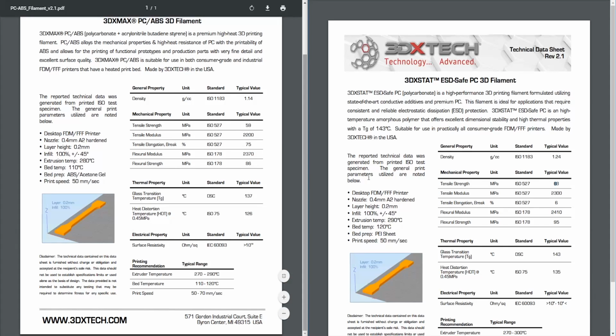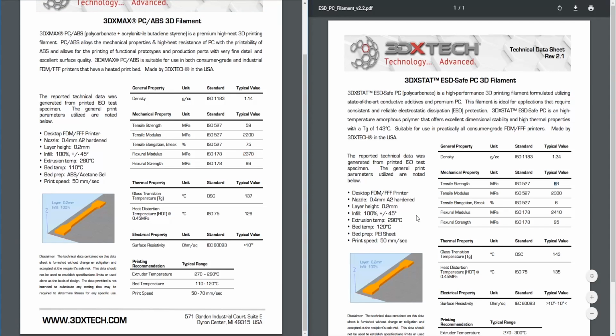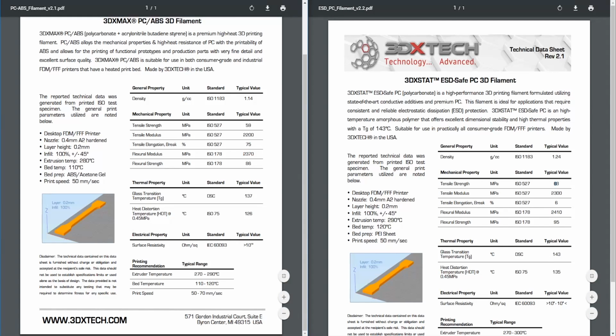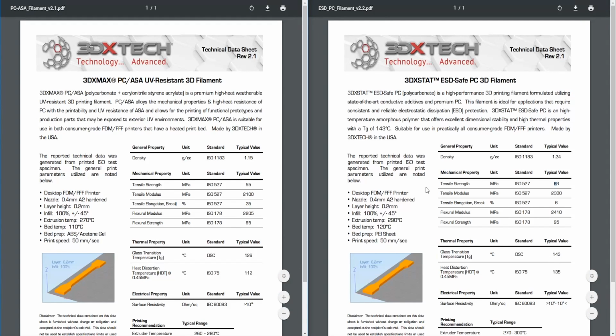68. Oh, more stiff. Okay, so standard's more stiff. So we have a little bit of loss in stiffness, but drastic gains in flex, and just a slight, like 40 megapascal drop in the flex stiffness, and then like 9 here, and then we lose a little bit of temperature stability. So again, polycarbonate ABS has way better mechanical material properties than the standard polycarbonate. Again, I don't know if that's because of the ESD additives.